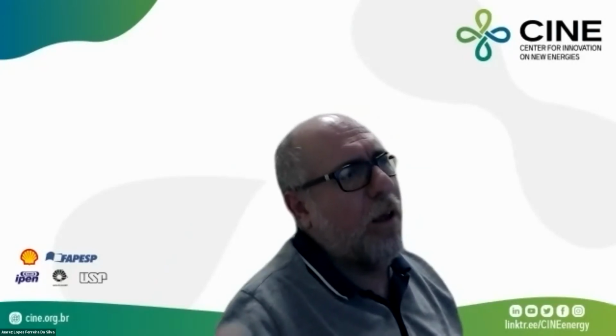And this vacancy is not going to change the Ceria oxidation state because of the charge neutrality, unless you have two vacancies close to Ceria. This means that if you know the oxygen vacancy induced along your synthesis process, then you are able to reach the Ceria 3+ and see how much Ceria is there. To get my point, it is the following: if you mix up La2O3 and CeO2, you don't form Ceria 3+. There's no way. Only if you have additional vacancies.